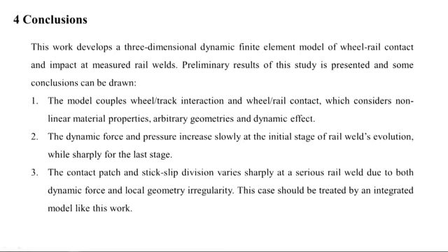To conclude, this work develops a three-dimensional dynamic FE model of wheel-rail contact and impact at rail welds. The model couples the wheel-rail interaction and wheel-rail contact with nonlinear material properties, arbitrary geometry, and dynamic effects. The dynamic force and pressure increase slowly at the initial stage but sharply at the late stage. The contact patch and stick-slip division vary sharply at a serious rail weld under both dynamic force and local irregularity, and this case should be treated by a integrated model like this work.